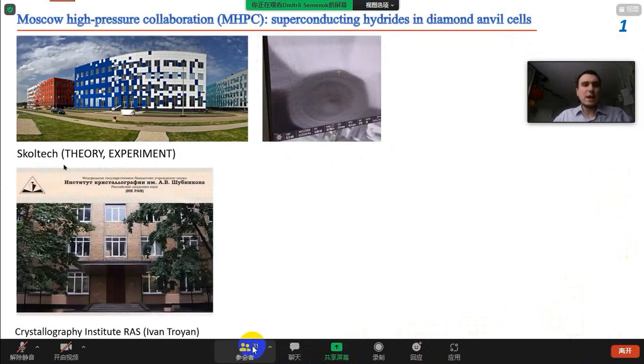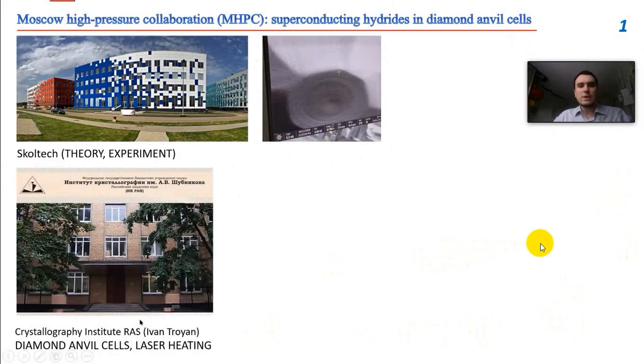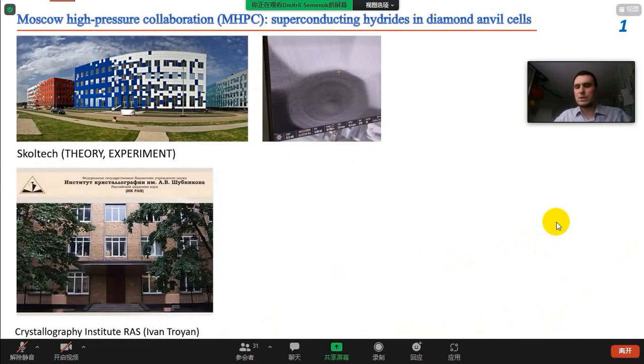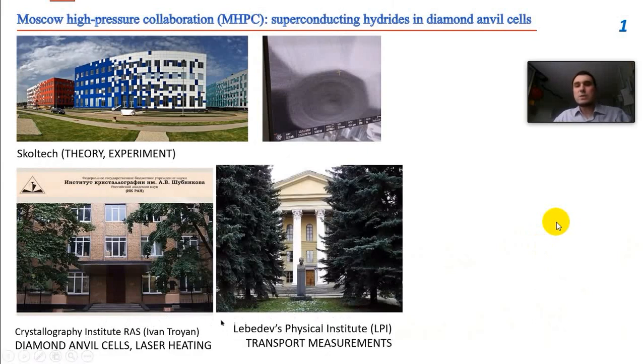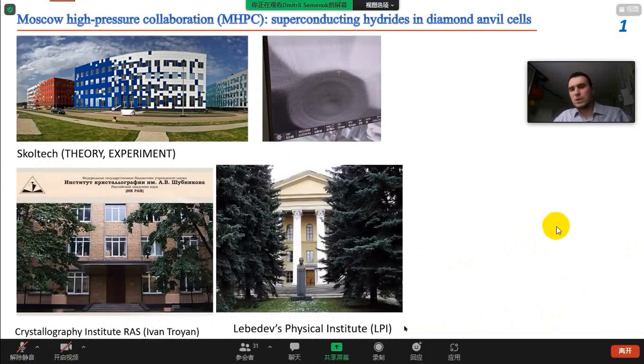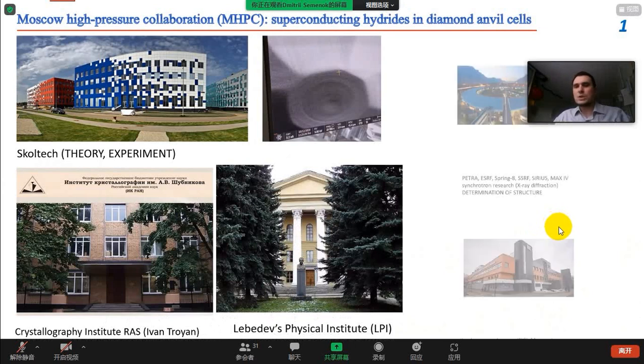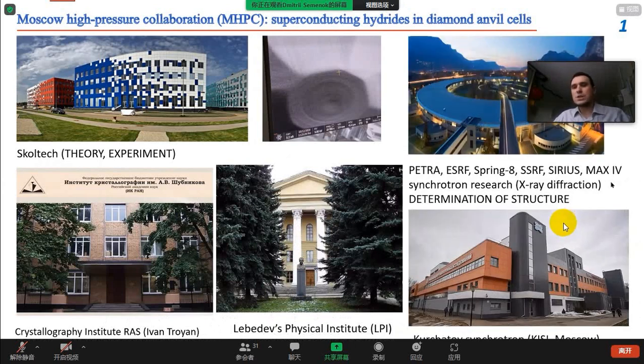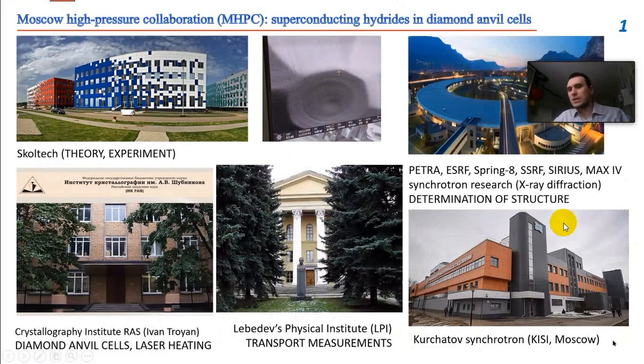And the high pressure diamond anvil cells are typically assembled in the Crystallography Institute of the Russian Academy of Science by Ivan Troyan. They also perform laser heating and synthesis of hydrogen-rich materials. Lebedev Physical Institute is responsible for electrical transport measurements and superconductivity in this project. And the structural investigations we are trying to do in Russia, at the Kurchatov synchrotron, where it's possible to work with low pressures.